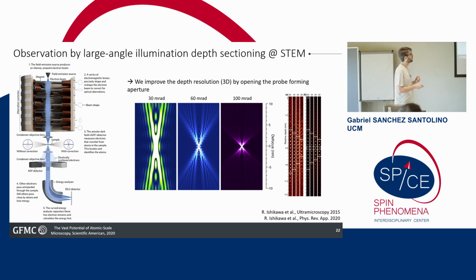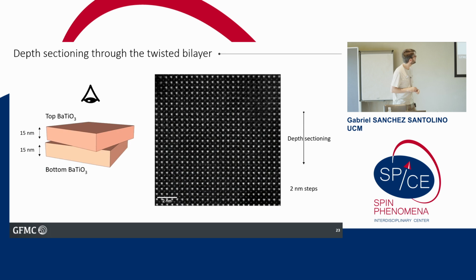And for example, we can identify the position of dopant atoms inside a crystal. Using this technique, which is called large angle illumination depth sectioning in the scanning transmission electron microscope, we can study these twisted ferroelectric structures. So this is a video of one of the samples. We are looking from the top, and we are going to change the defocus of the probe, doing these depth sectioning experiments from the top layer to the interface of the two layers, and then to the bottom layer.